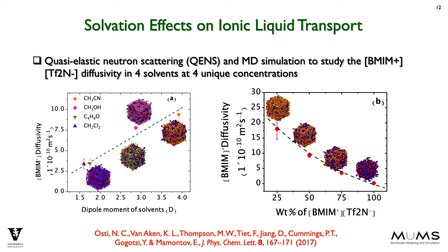We first performed combined quasi-elastic neutron scattering plus molecular dynamics studies of the ionic liquid BMIM-TF2N, BMIM bistriflimide, dissolved in four organic solvents, measuring the diffusivity of the BMIM cation via QENS. The four solvents shown in the figure at left were acetonitrile, methanol, tetrahydrofuran, and dichloromethane. The BMIM diffusivity measured by QENS was found to increase with solvent dipole moment, as shown in the figure at left.